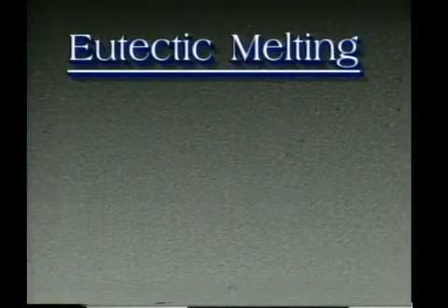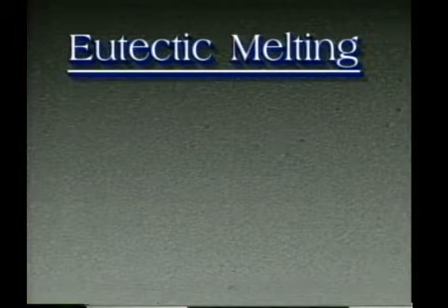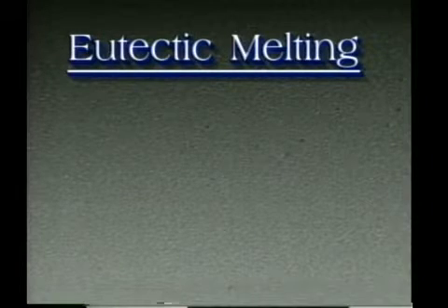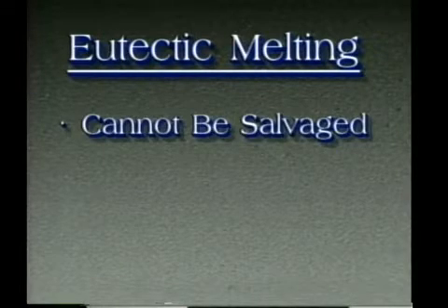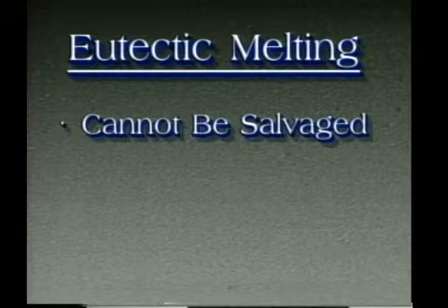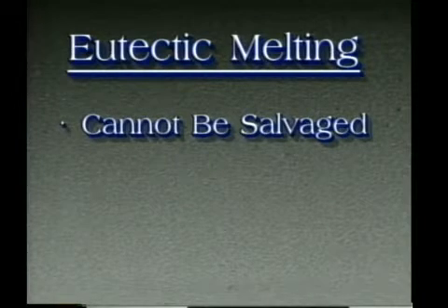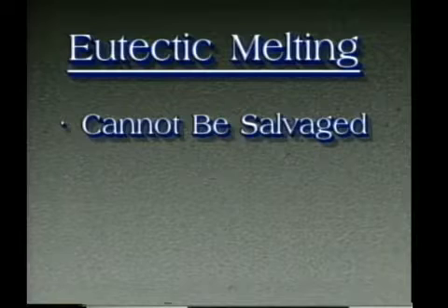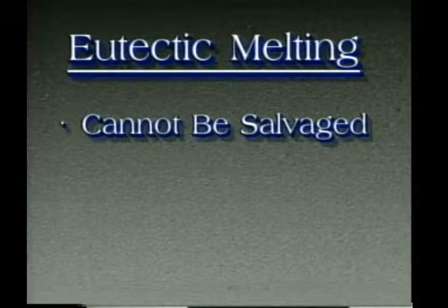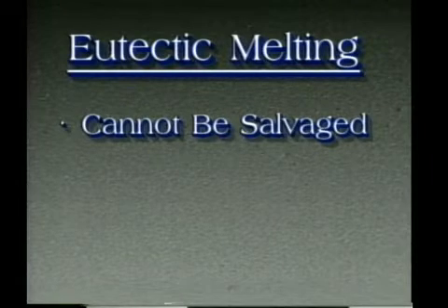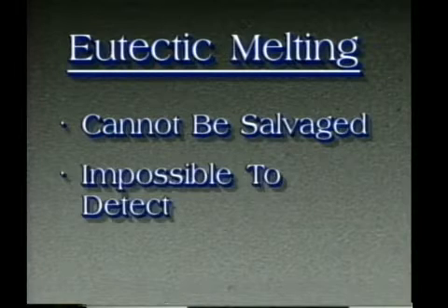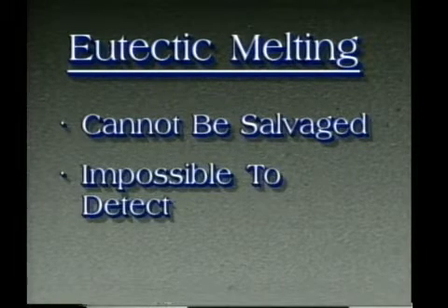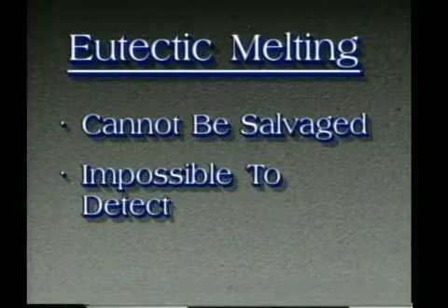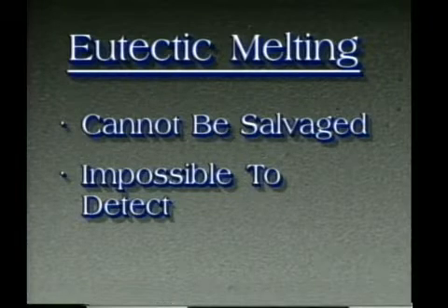The problem of eutectic melting is extremely serious because of two main reasons. One, it is a condition that cannot be salvaged by subsequent reheatment. Once the condition has been created by careless solution heat treatment, the only recourse in most instances is to scrap the material. Two, it is nearly impossible to detect the condition by normal non-destructive testing techniques.